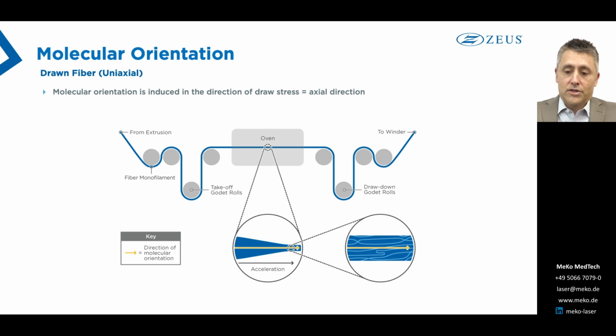In drawn fiber, the molecular orientation is uniaxial, meaning it's in one direction, and that's in the axial direction or the machine direction. So if you take a look at this simplified schematic of a fiber drawing process, let's go straight to the end there where you see that second inset with the fiber being aligned. This is really what we're after, the alignment or the orientation of the polymer chains. So this is achieved by drawing or stretching the fiber under certain conditions.